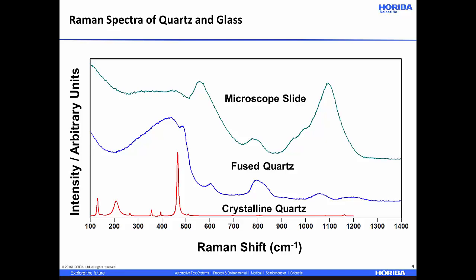Here are spectra of similar, if not identical, materials. In the case of quartz, they're the same composition. You see the Raman spectrum of crystalline quartz, which consists of very sharp, narrow Raman bands, and in contrast, look at the fused quartz — same chemical composition but a different solid-state structure. It is amorphous, a glassy material. Consequently, it does not have long-range translational symmetry, and now all the phonons within the Brillouin zone become Raman active and are sampled, so we see Raman scattering over a very broad range of wave numbers.